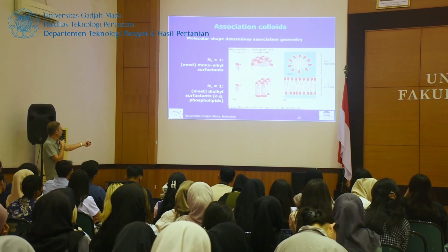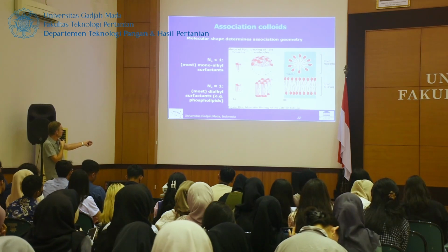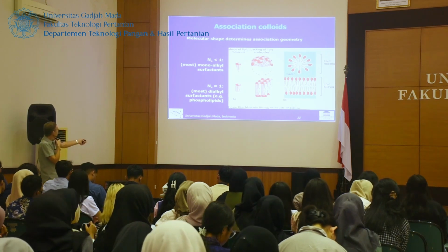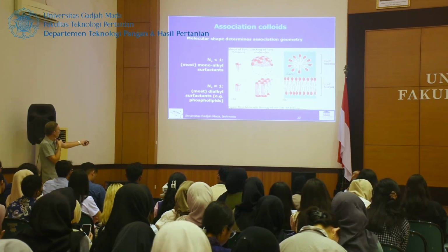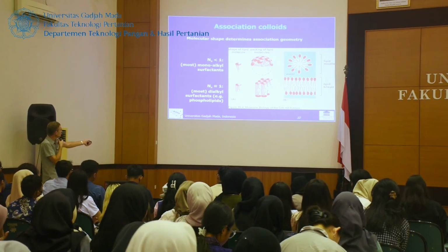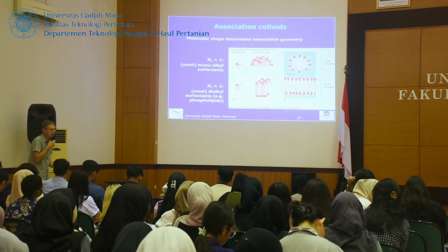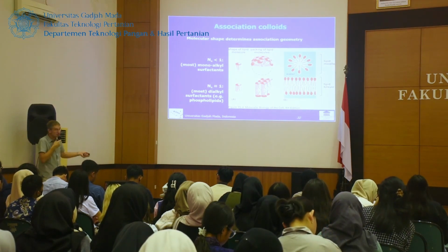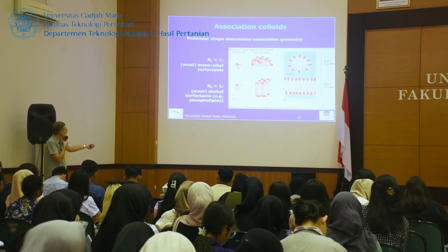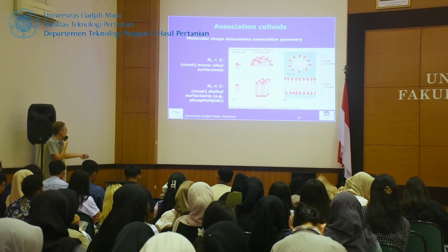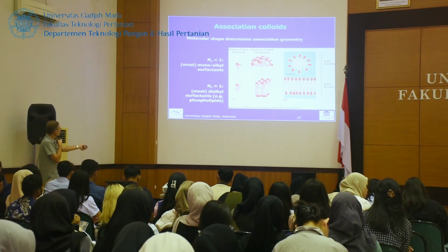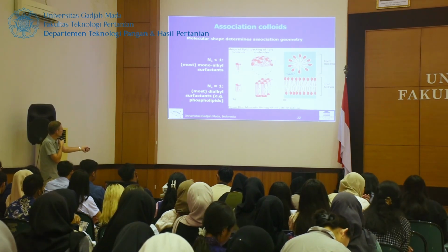And so you will typically have this for simple surfactants that only have one alkyl chain for every hydrophilic head group. So it means in this case we have a surfactant number below 1, because the cross-sectional area of the hydrophobic part is smaller than the cross-sectional area over there. Whereas, for instance, phospholipids in water, and in general most surfactants that have two long alkyl chains, have a kind of cylindrical shape here. So here your packing parameter, the surfactant number, is about 1.